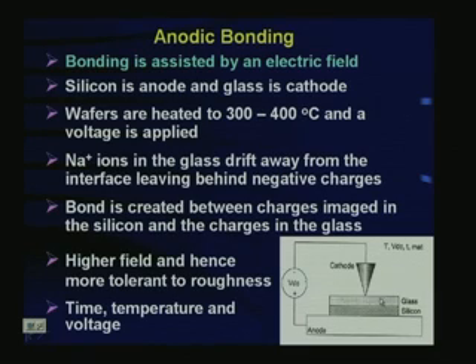So, positive sodium ions in the glass are drifted away from the interface, as a result of which a negative charge will be left at the interface. These negative charges in the glass induce the opposite charge in silicon, and as a result they create a certain depletion layer. This layer is extremely thin, and because of that a high field is generated at the interface, and that high field basically prompts the bonding process. So, this is the basic technology in the anodic bonding technique.